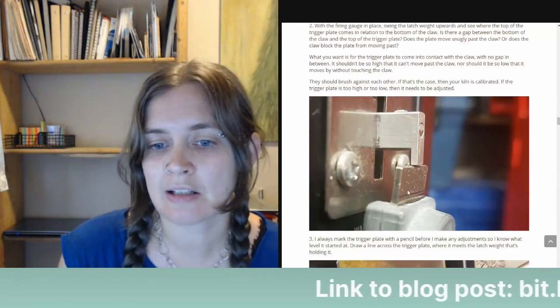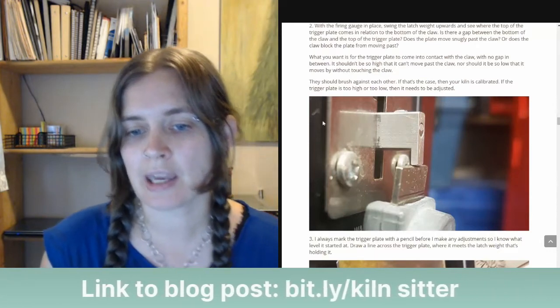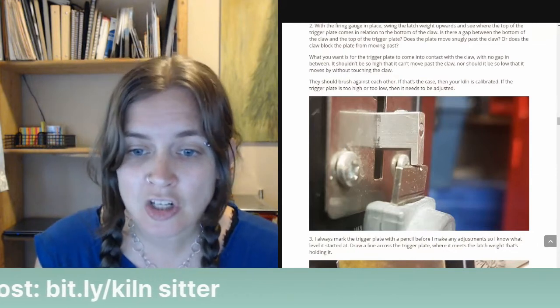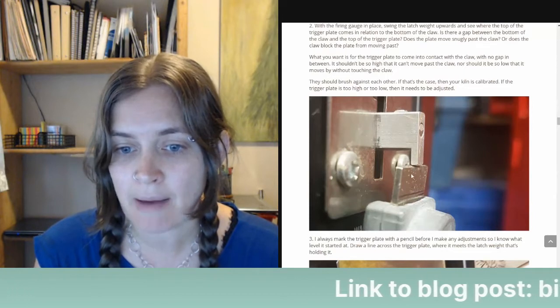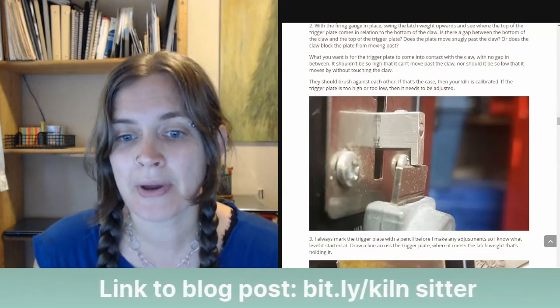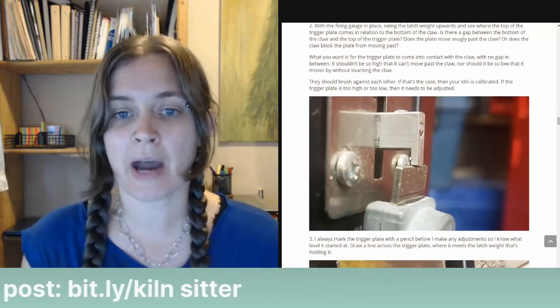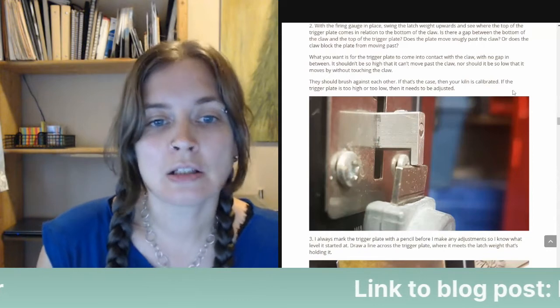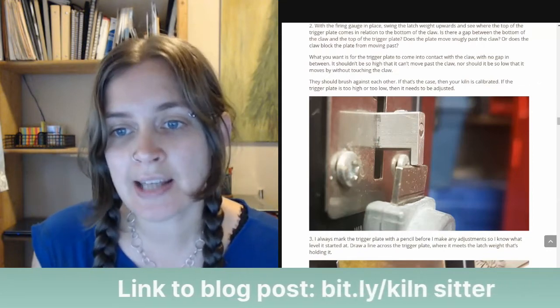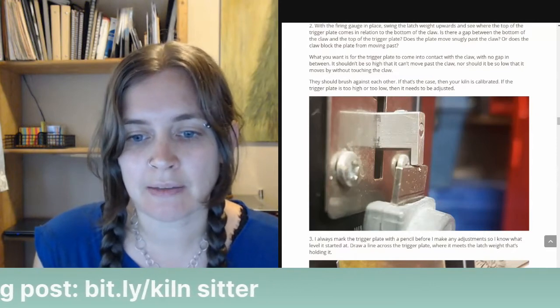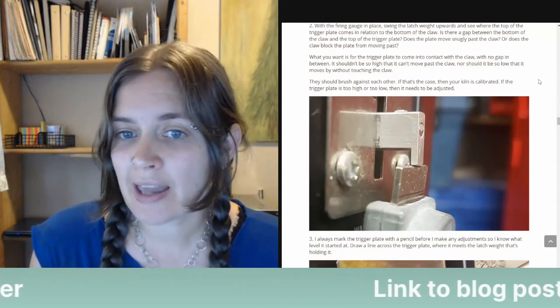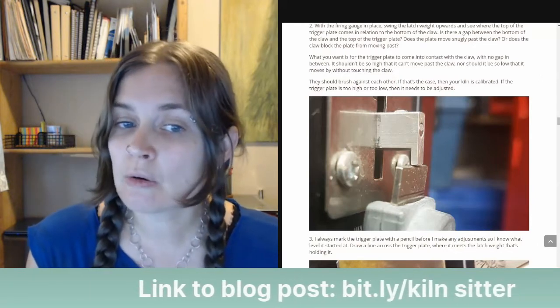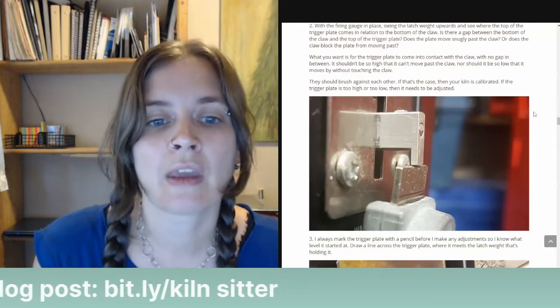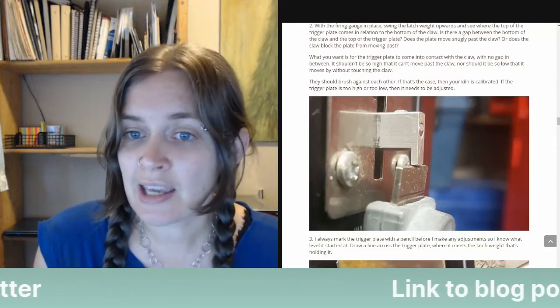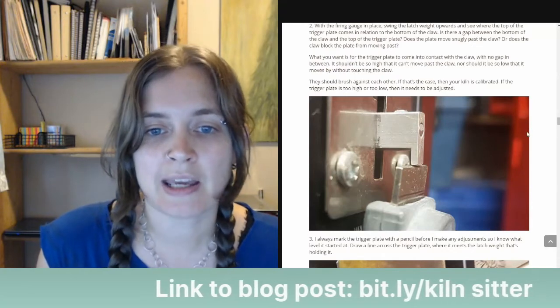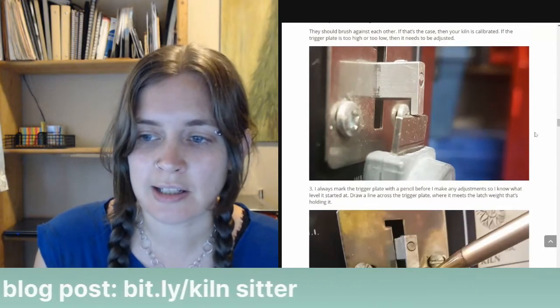So this trigger plate here slides up and down. And so when you have your firing gauge in place, this could be just brushing the bottom of the claw, or there could be a gap here, or this could be up and blocked by the claw from falling down. So what you want is for the trigger plate to come into contact with the claw with no gap in between, like you see here. It shouldn't be so high that it can't move past the claw, nor should it be so low that it moves by without touching the claw. They should brush against each other. If that's the case, then your kiln is calibrated. If the trigger plate is too high or too low, then it needs to be adjusted.